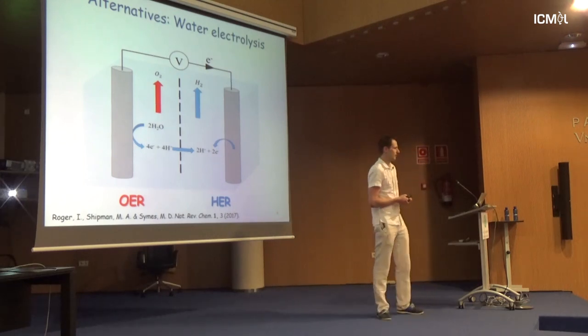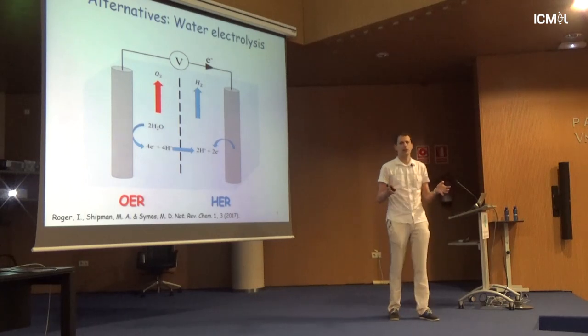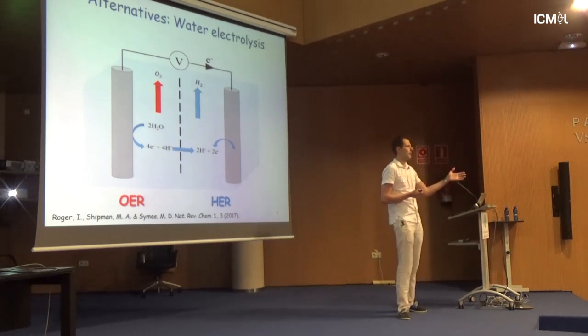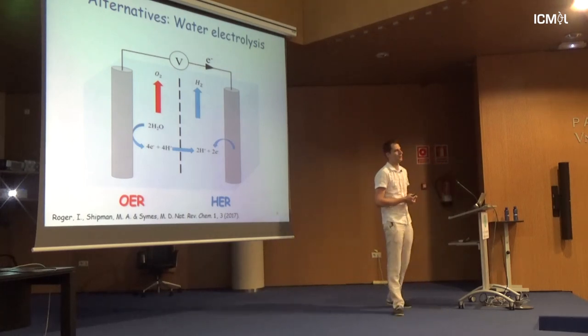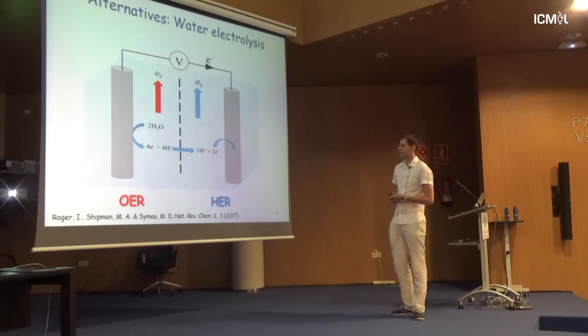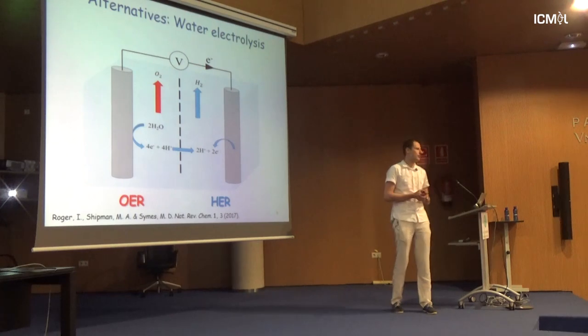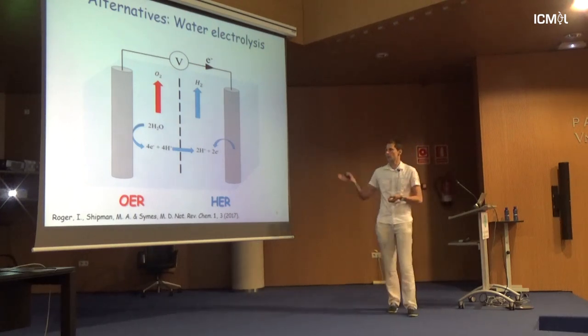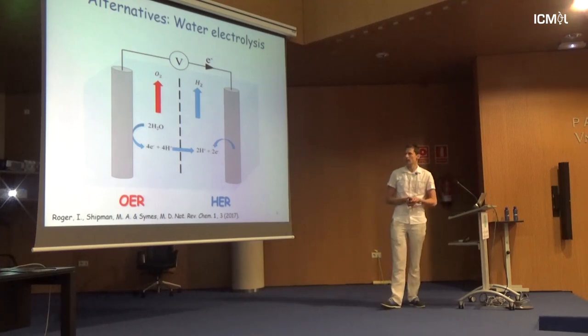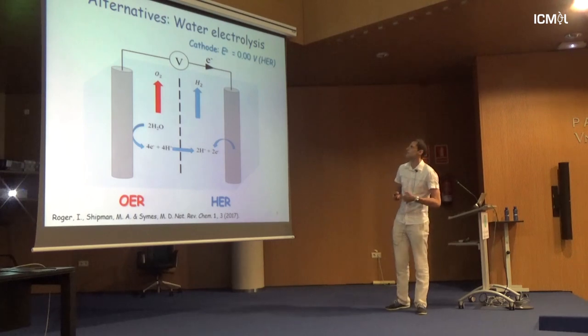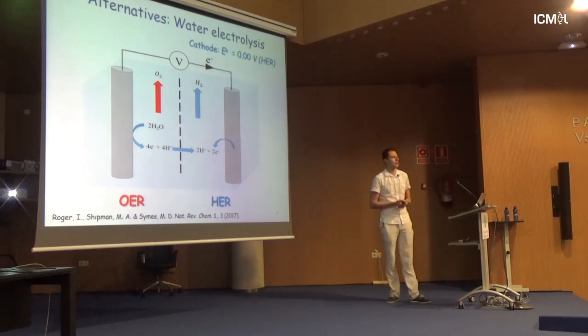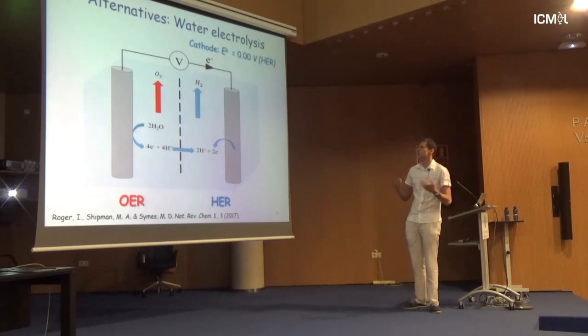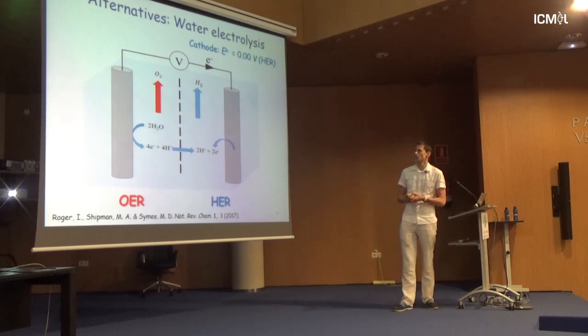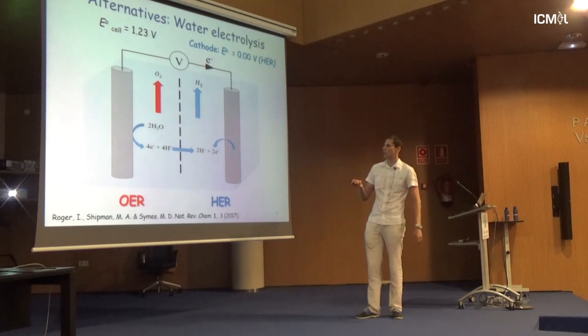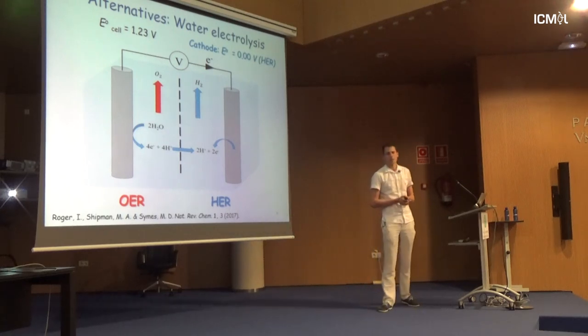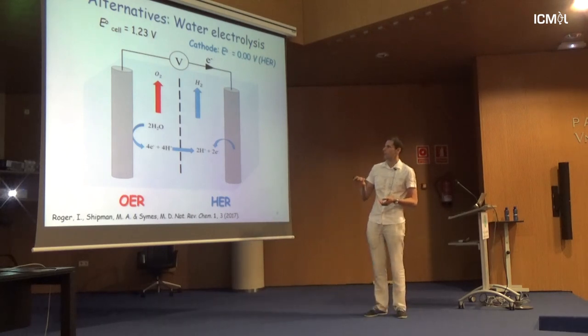Electrolysis of water is quite impractical. So what is done typically, you can either use alkaline conditions, so very high pH, or you can use very low pH, so acidic conditions. If you use acidic conditions to reduce hydrogen, you just need to give an extra electron to a proton, and in theory it should turn into hydrogen. Very, very simple. So effectively, if you work in acidic solutions, you need very, very low energy in order to evolve hydrogen. So most of your energy consumption will go for production of oxygen. Okay?